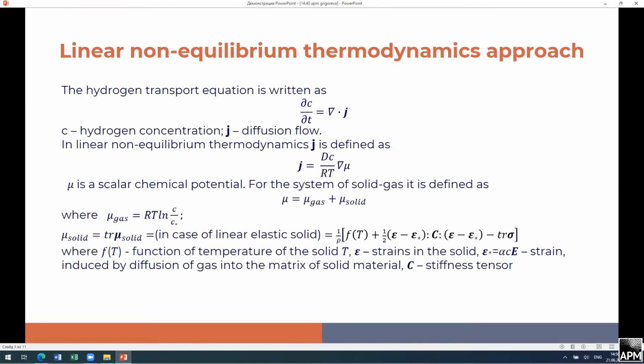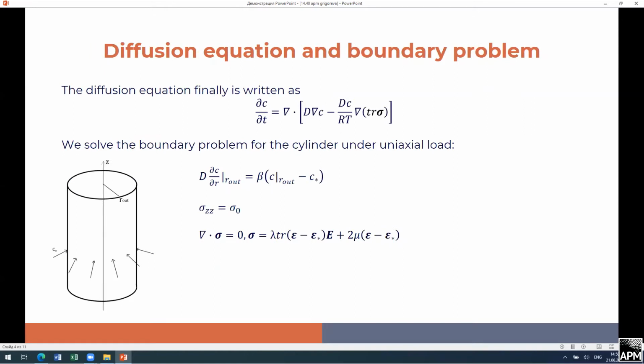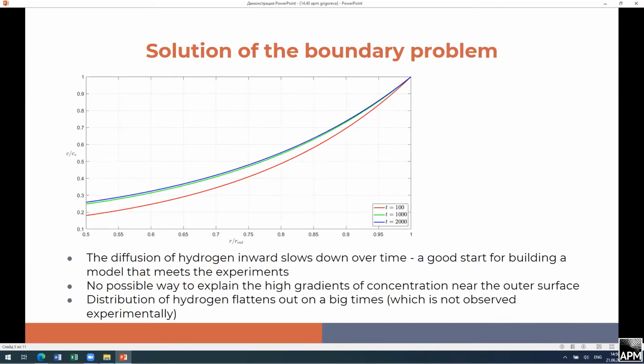So finally, in case of a linear elastic solid, we obtain the diffusion equation and solve the boundary problem for the cylinder with a prescribed axial load and flow on the surface. And also we say that we have diffusion strains, induced by the diffusion of the hydrogen inside. But again, we solve the linear elastic problem. So in this case, we obtain some curves that show that first the diffusion of the hydrogen slows over time. It's quite a good start for building a physical model, not a phenomenological one.